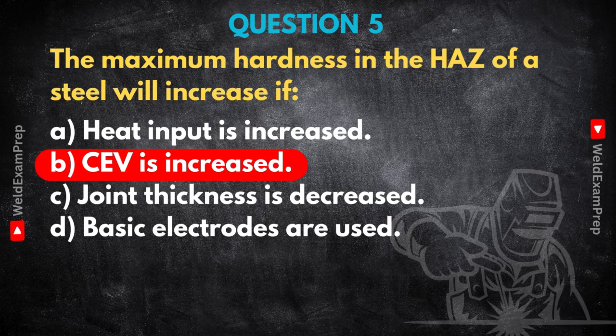So for you, the welding inspector, looking at a material specification, seeing that CEV number, how does knowing that practically help you manage risk before or during welding? Oh, it's absolutely fundamental for managing risk. If you see a material certificate or a WPS referencing a steel with a high CEV, flags should go up. You immediately know this steel is more sensitive. It's more likely to form that hard, brittle HAZ and potentially crack if you're not careful. So that knowledge directly informs your decisions, or the decisions you ensure are being made.